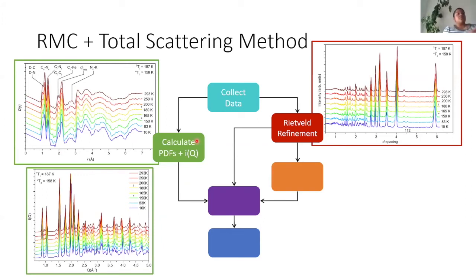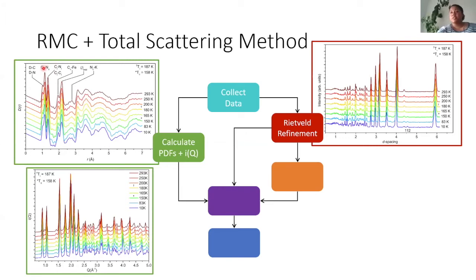From that same scattering data, we can also get the scattering function S(Q) and its real space Fourier transform, the pair distribution function. The pair distribution function is just a histogram of interatomic separations. The first peak at about 1.1 Å tells us the distance between deuterium and carbon, and deuterium and nitrogen in the imidazole ring. The next peak at 1.15 Å is the distance between the cyanide linkers. 1.35 Å is the carbon-nitrogen distance in the imidazole rings. As we go to higher distances, it becomes harder to accurately identify which contribution belongs to which atom pair.